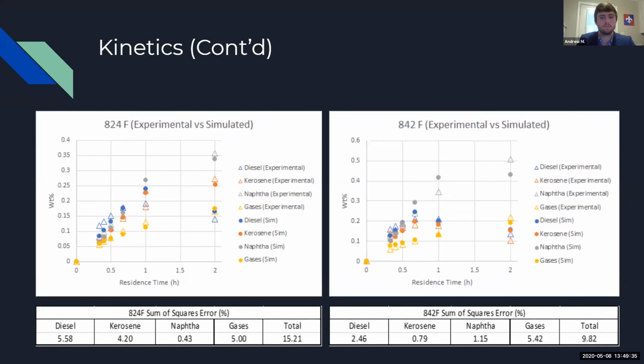Now the top 2 temperatures were a little different. The diesel for 824 began to go down due to the degradation reactions. So it produced more kerosene and naphtha at the higher residence times. And then the same thing happened for 842, but it wasn't just diesel, it was diesel and kerosene. So we made a lot more naphtha at 842. Then for these 2 temperatures, 824, sum of squares there is about 15%, whereas 842 is about 10%.